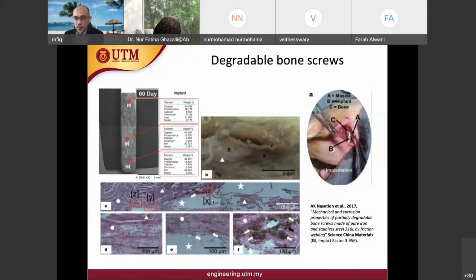The pure iron rod and the stainless steel 316L rod, we fuse them using friction welding, and so once it is fused, we will have three different material properties. So one rod consists of three different properties. One, the property of the pure iron itself, and the second one is the property of the 316L itself. And of course, when you fuse them, you have this heat affected zone in between these two materials with its own properties. Yeah? So we have various properties and various composition of materials, and we use it as a pin.